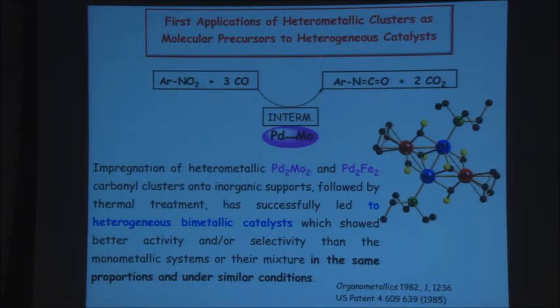Now, the beauty of this reaction here is not only the simplicity, but it is telling a lot about the nature of the catalyst. Because molybdenum provides activity, palladium provides selectivity. If both are high, you get isocyanates in very high yields and very high purity. Otherwise, if you have leaching of one of the two metals, you immediately see the conversion drop, the activity drop, or the selectivity. So you can have a chemical tool readily available here.